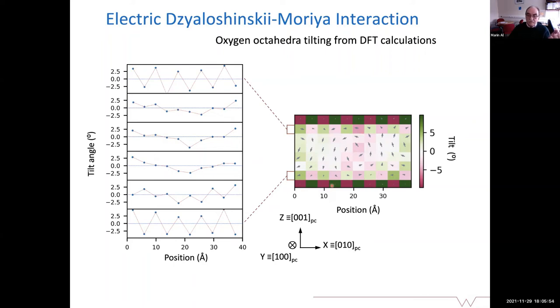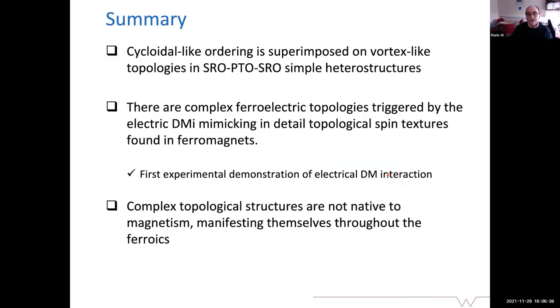The first unit cell, the strontium ruthenate, patterns the oxygen octahedra tilting into the lead titanate. I must mention that lead titanate has zero tilting. It's not a tilted structure, it's not like bismuth ferrite, and it doesn't like to be tilted. So we found a strong tilting in the middle of the vortex core, which is quite normal because there is a lot of strain there. And that actually might generate the cycloidal ordering, which is due to Dzyaloshinskii Moriya interaction at the interface.